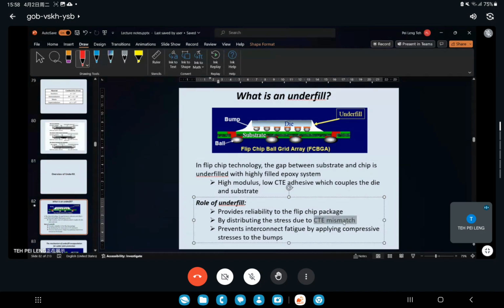I hope you still remember what this is. CTE mismatch means a difference in CTE value, a difference in shrinkage and expansion rate. So the die, as I said, is only 2 to 3 ppm per degree Celsius. The substrate is polymer and can go up to 80 to 100 ppm per degree Celsius. So it's a huge difference. Metal is in between these two, around 40, or 30, 40 or 20, depending on what type of material. So the CTE value is different. That's why you have CTE mismatch, so it will generate thermal stress.